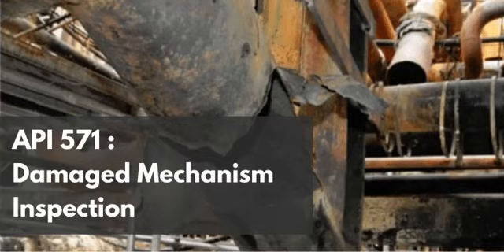Or consider the shifting global crude slates. Right. As refineries process heavier, more challenging crudes with higher nitrogen content, the ammonia generation in the cracking units will inevitably rise, pushing that sour water pH higher and higher. A system that has comfortably operated at a safe pH of 7.2 for decades could slowly creep into the alkaline danger zone. The metallurgical physics don't change, but the operational realities surrounding these aging assets are shifting constantly. Making the detection and mitigation of this microscopic spiderweb more critical than ever.